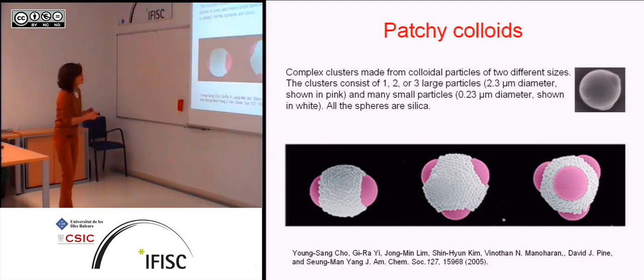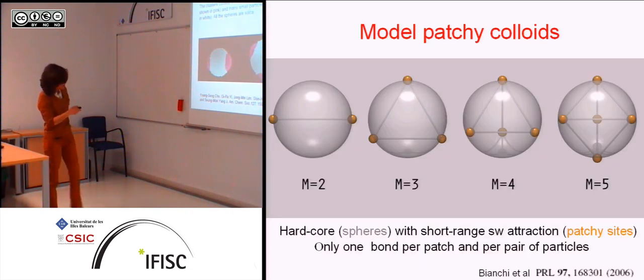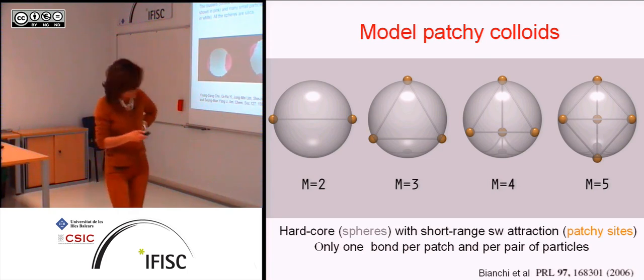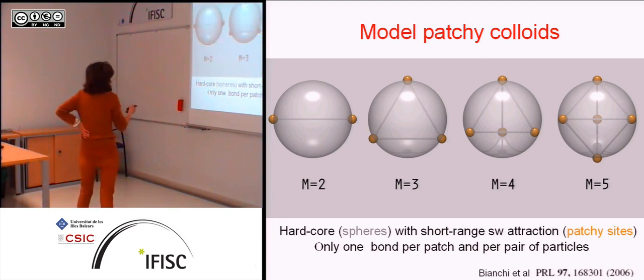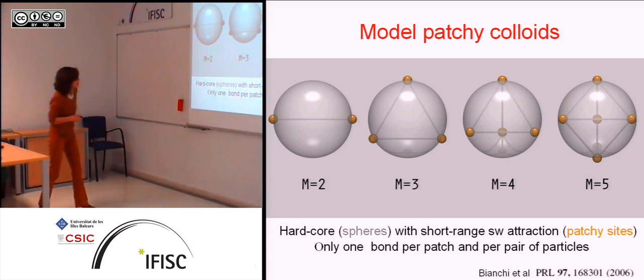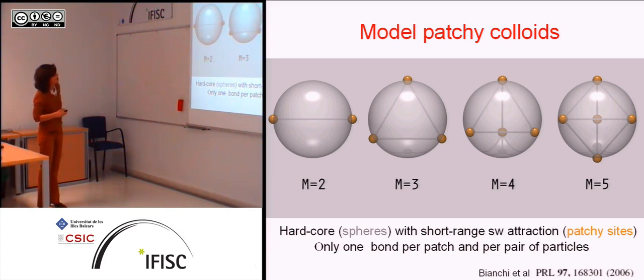And these are real colloids that have these properties. They have spots, in fact, this is one sphere and it's covered by lots of little spheres. So this is a 2-spot, this is a 3-spot, 4-spot colloids. These things exist. They don't exist in large quantities, but of course this has been modeled already by a group in Rome led by Francesco Sciortino, and they've been looking at these model patchy colloids by simulation, also using some theory. But the models are very simple. Spherical hard cores and bonding sites. In this model, all the bonding sites are the same.